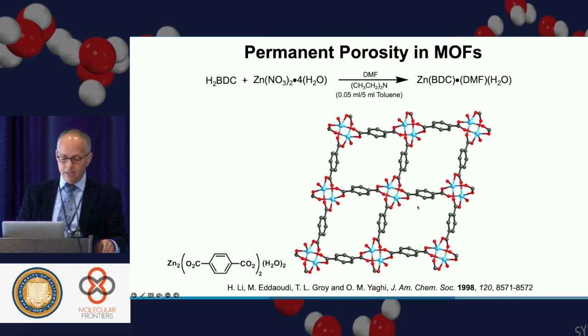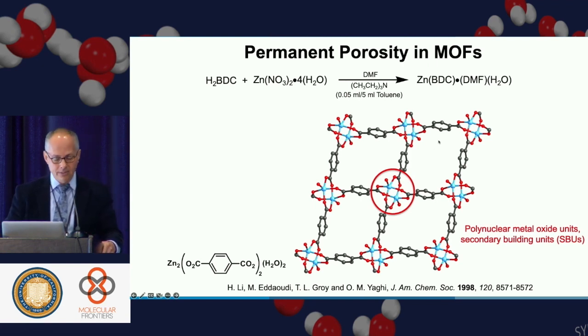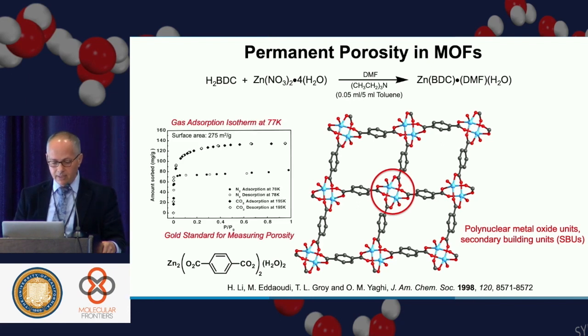So this is what we made. And this is called in inorganic chemistry a paddle wheel. It's linked by organics. And when you make this, there are DMF molecules filling up the pores. And the big question was, could we remove the DMF and will the structures remain open and rigid? And the answer to that came from measuring a gas adsorption isotherm, which has to be done at 77 Kelvin. You evacuate the pores and you expose them to tiny amounts of nitrogen. You see the nitrogen going in the dark circles, coming out in the open circles. It's very reversible. It has a type 1 isotherm. And you can do this also with CO2 just to show that, in fact, this structure can remain open in the absence of anything in the pores.